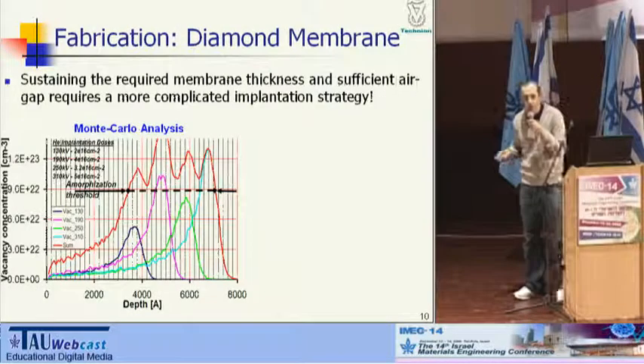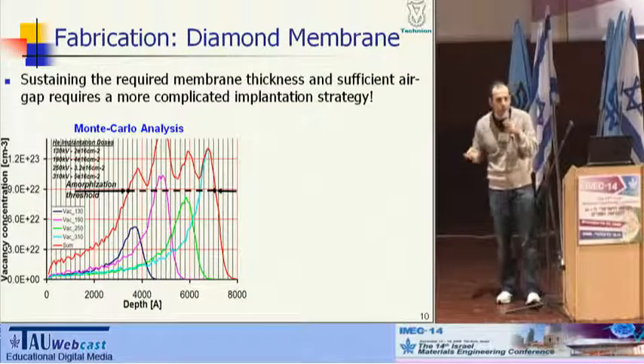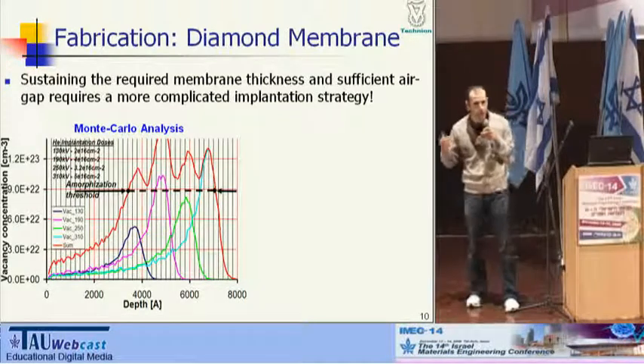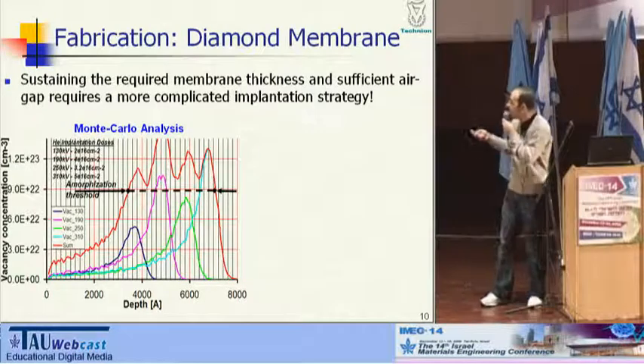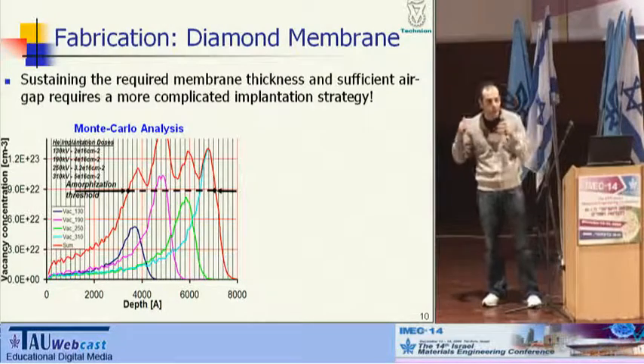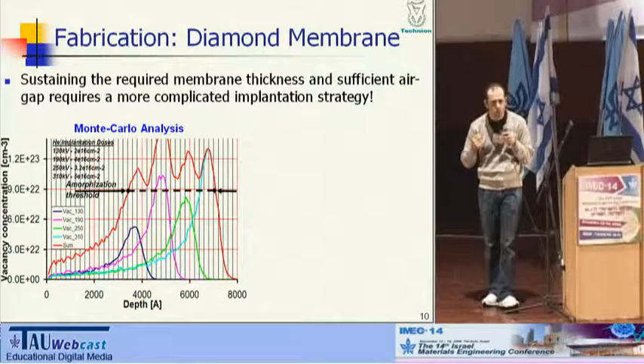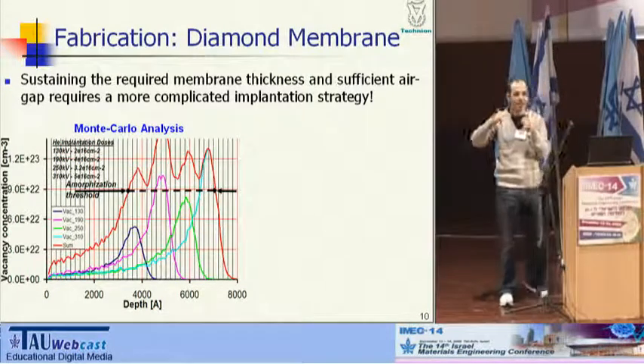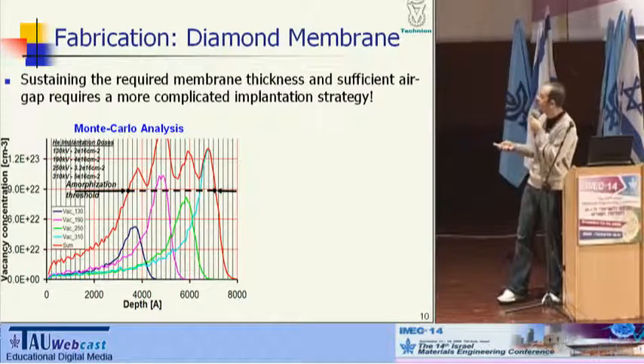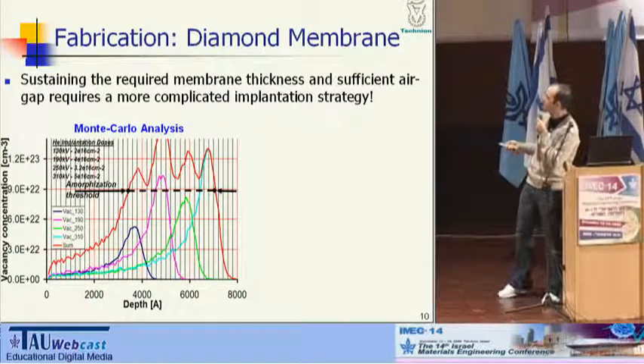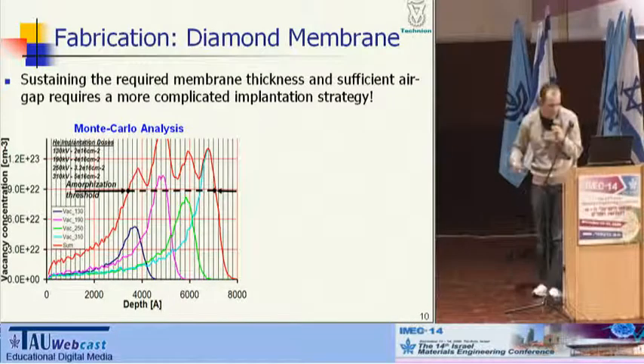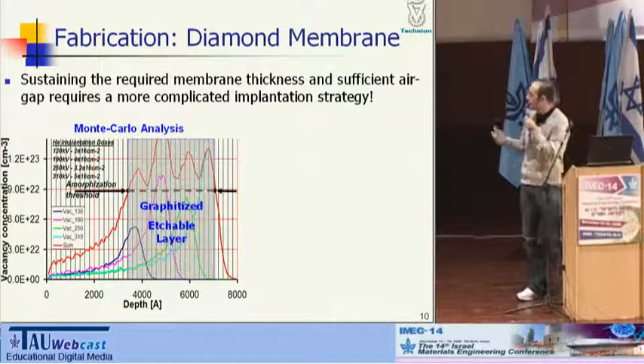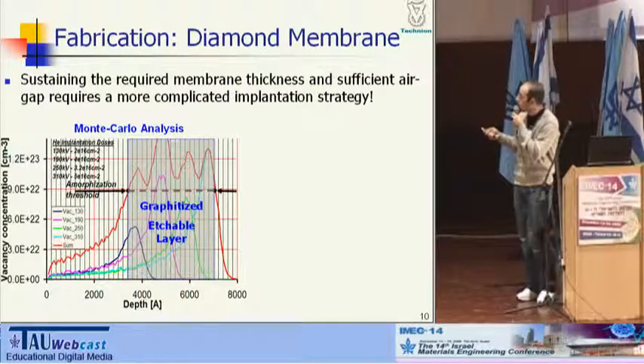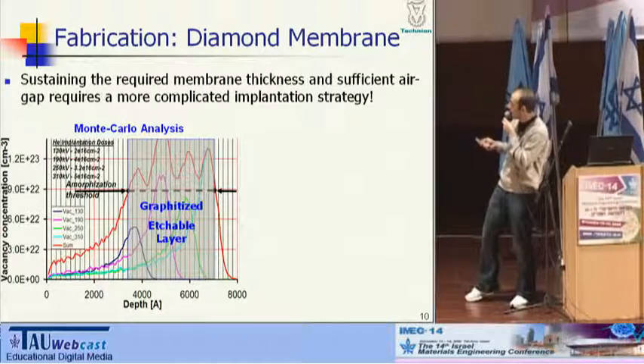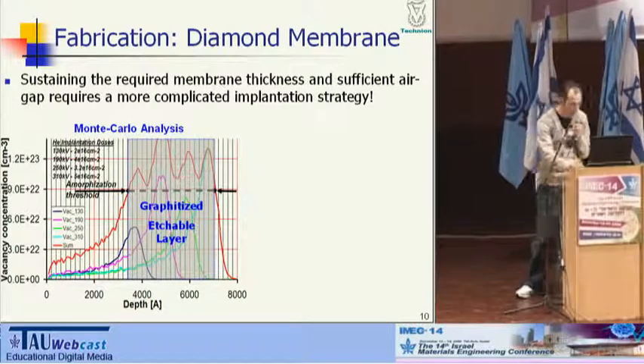Now, this graphical picture is somewhat more complicated, because for the photonic crystal to operate in the visible range, we've got to have a sufficiently thick membrane with a large air gap underneath to localize the light sufficiently far from the substrate. So we have the following implantation strategy. There are 4 helium implantations. In red is the sum damage for the membrane. When the damage density is higher than the threshold, it turns into a graphitized layer under thermal annealing, and this layer can be etched out.